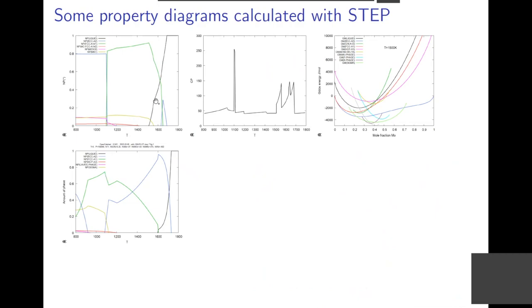And I show you some figures of a step calculation. This is for a high-speed steel where you have a liquid at high temperature, and you have a small region with BCC phase forming and so on. This is from the same calculation: you plot the heat capacity, and this includes the latent heat for the phase transformations also. This is a special type of calculation where you plot just the Gibbs energy curves. This is not equilibrium at all. You typically use this a lot when you do assessments, when you want to understand how the different phases behave. This is another step calculation for a high alloyed chromium steel.